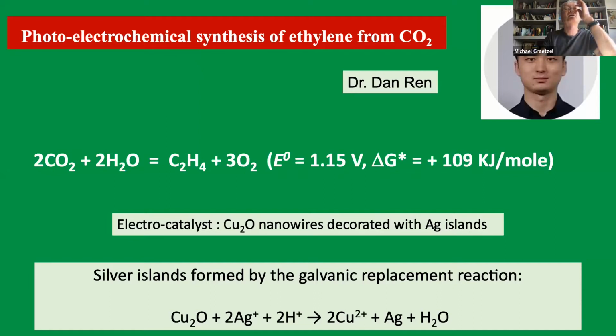And finally, our favorite reaction is the generation of ethylene, following the proposition that was kindly made by the chairman of Saudi Aramco at one Gordon conference, which I attended in Hong Kong. And so we use here silver. It's actually cuprous oxide nanowires that you use, but the cuprous oxide under operating conditions is largely reduced to copper, and actually there are some silver islands on that copper. That's the catalyst we used here.